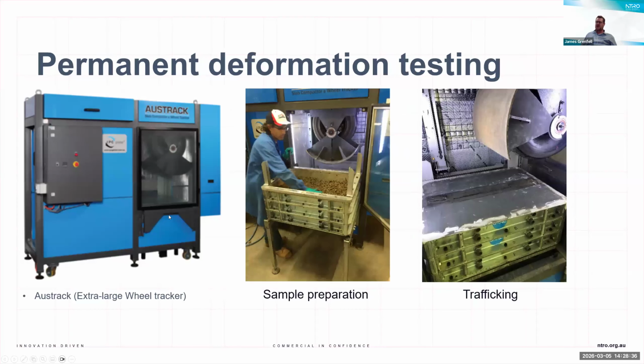We have a device here in the laboratory at NTRO, which we call Austrack, or the extra large wheel tracking device. Basically, we can make up slabs of material that are 700 millimeters long, 500 millimeters wide, up to 300 millimeters deep. We compact in 50 millimeter layers, so 6 layers of 50 millimeters make up a 300 millimeter depth slab. We seal the slab with an epoxy to hold the moisture content constant, and then traffic it with a pneumatic wheel load at 8 kilonewtons for 40,000 passes to understand how it performs in the laboratory. And we've got a lot of indication of how that scales to field performance.